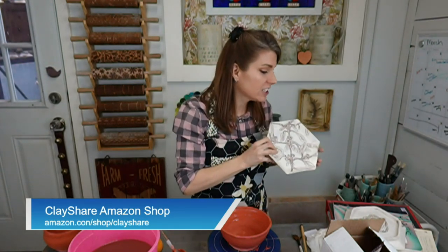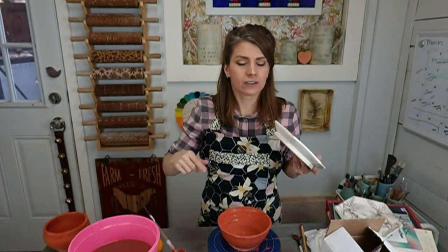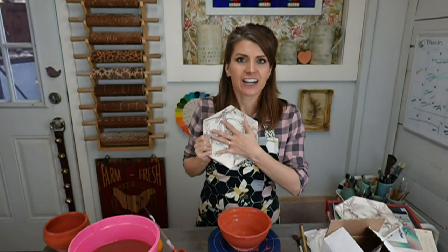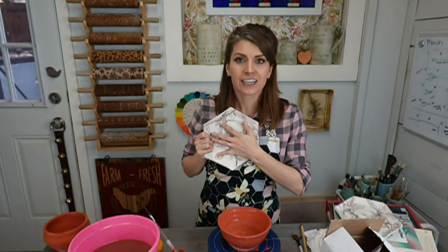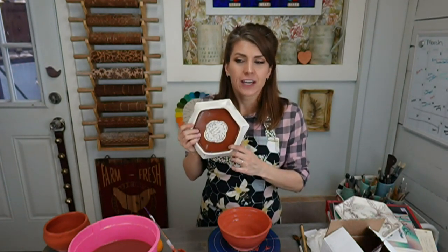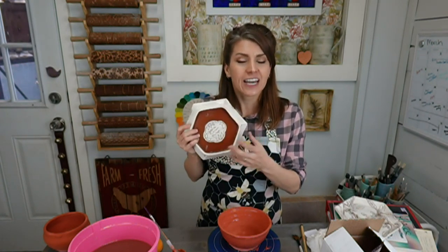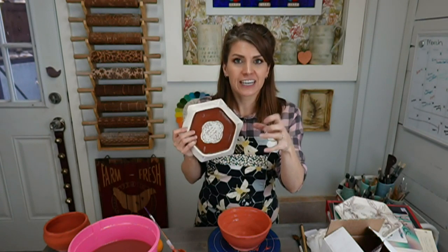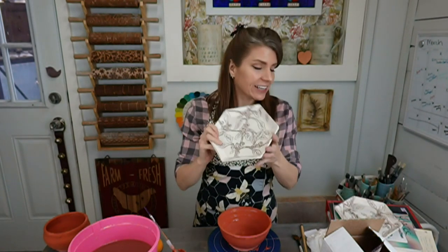So yeah, I love her work. She's pretty awesome. And when I was trying to take a low fire earthenware clay higher, she was my resource. She was the one I went to get the information I needed to know that I could push the clay hotter. And what I found through testing is that the terracottas, the red earthenwares, you can push. They get more brittle as they get hotter, but they still can go to cone 1 easily, and it actually vitrifies them. So when you take an earthenware clay and push it to cone 1 or cone 2, you vitrify the clay, and that erases the issue with them being porous. So it's a workaround, right? Now the white clay, the white earthenware, you can't really push. You really have to keep that at low firing temps, or at least that's what I found.